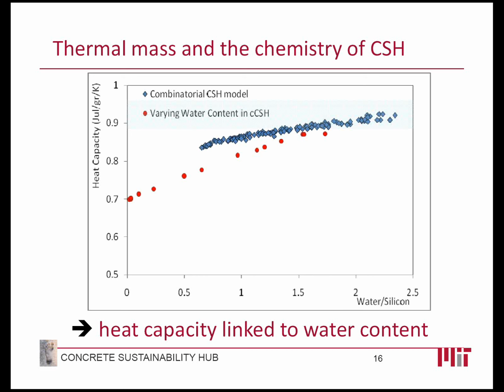So this is why we are stating that the heat capacity of cement is actually linked to the amount of water in CSH. Now, to tell you the whole story, it is very hard to dry the system completely in CSH. We found that there is some part of the water that is very difficult to take out of the system just because it is very chemically bonded to CSH. So these are, by the way, simulation results.